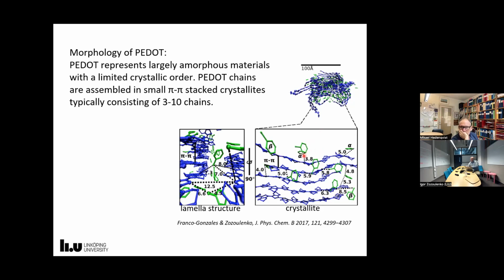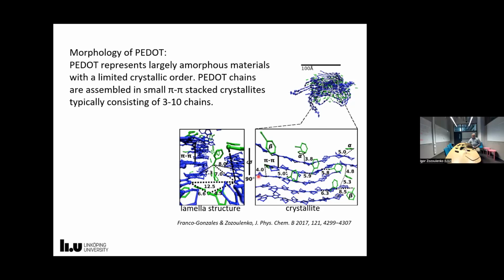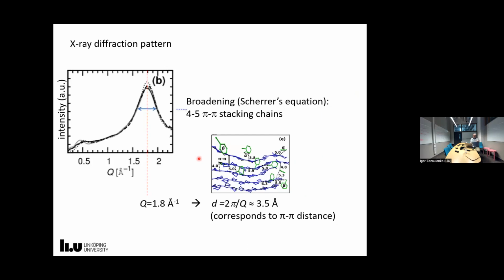So in this case, typically you have 3 to 10 chains in one crystallite, and then these crystallites form so-called lamellas. So here you have two crystallites parallel to each other, and this structure is called lamellas. So this would be a typical morphology of PEDOT, in this case PEDOT tosylate, but as I said, it's very typical for all other conducting polymers.